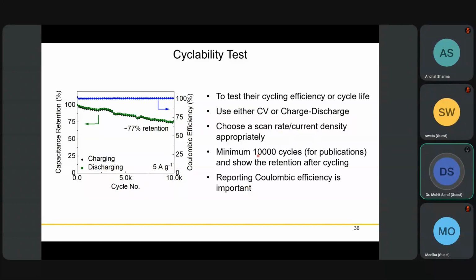This is not a strong recommendation, but at least from a publication point of view, you have to do 10,000 cycles and show the changes before and after cycling. And of course, the Coulombic efficiency is very important.